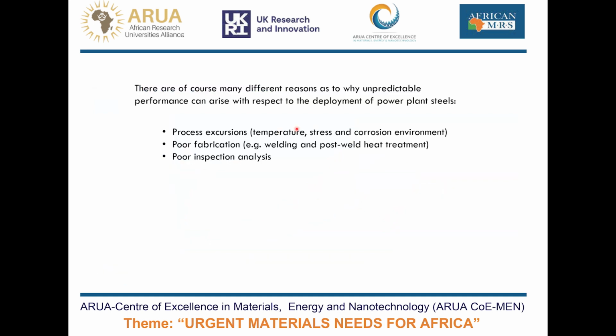So there are, of course, many different reasons as to why unpredictable performance can arise, not only perhaps simply in a different starting state of the material. There are process excursions, for example, the temperature, stress, and corrosion environment could differ over periods of time in service. We could have poor fabrication, for example, welding and post-weld treatment, which may well be unknown and therefore unpredictable features. And of course, there could also be poor inspection analysis where we think something is good, but it's not good. So what do we need to address these issues?